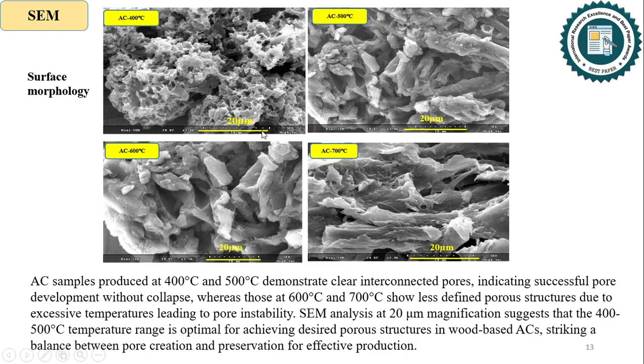Then the surface morphology of activated carbons was investigated by SEM. Activated carbon samples produced at 400 degrees and 500 degrees centigrade demonstrate clear interconnected pores, indicating successful pore development without collapse, whereas those at 600 degrees and 700 degrees centigrade show less defined porous structures due to excessive temperature leading to pore instability. SEM analysis at 20 micrometer magnification suggests that the 400 degrees and 500 degrees centigrade temperature range is optimal for achieving desired porous structures in wood-based activated carbons, striking a balance between pore creation and preservation for